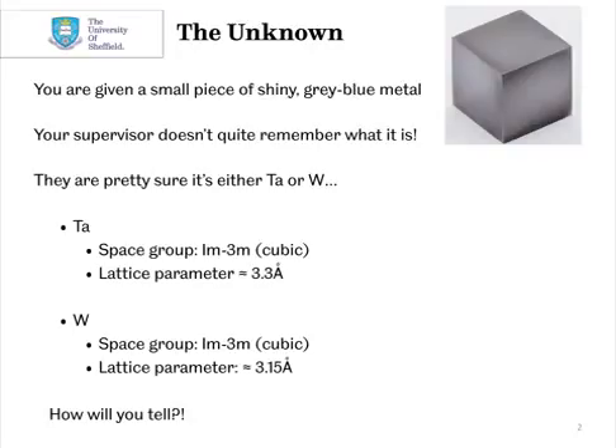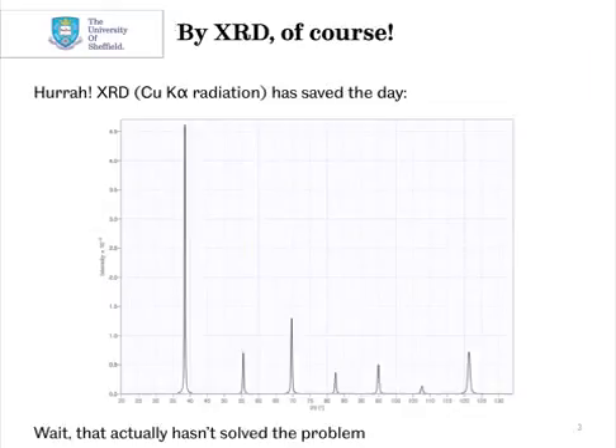Tantalum and tungsten both have a very similar space group, Im-3m, both body-centered cubic, and the lattice parameters are quite similar as well: 3.3 angstroms for tantalum and around 3.15 angstroms for tungsten. So how are you going to tell what this metal is? Well, the one thing you can do, obviously, is do some XRD on it.